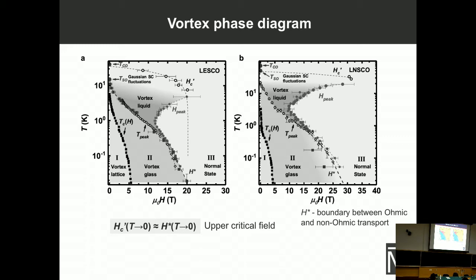So by doing the usual quadratic in temperature fits, we see that this extrapolates really surprisingly into this same field where non-ohmic behavior vanishes. So this supports our identification of this field H star in the limit of low temperatures as the upper critical field. So what happens here in this state where, based on these measurements, we do not see any evidence of superconductivity?